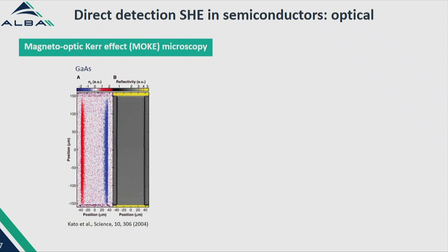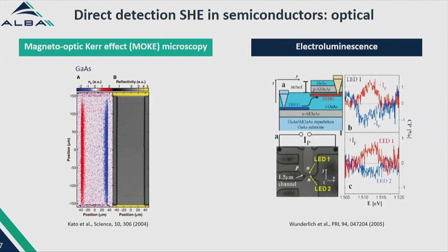And shortly thereafter, in a slightly different experiment, but also by optical means, the spin Hall effect was detected by measuring the angle-dependent polarization of light emitted by electroluminescence in two ends of a two-dimensional hole gas with spin-orbit coupling, in a stack forming a clever coplanar design of PN junction LEDs.